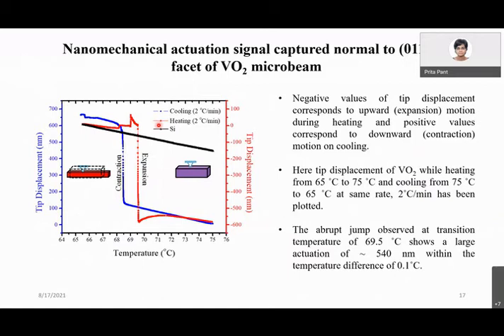Yes, we keep the lowest possible load. We tried with different loads, I think the 10 micronewton and 25 micronewton. We know that the penetration depth is very small at that particular load for VO2. After that, we are essentially keeping the same load constant, only changing the temperature.